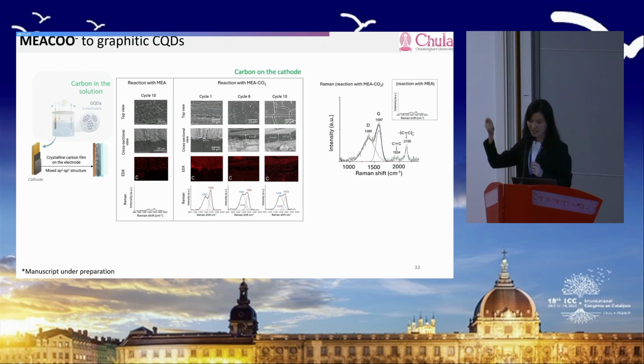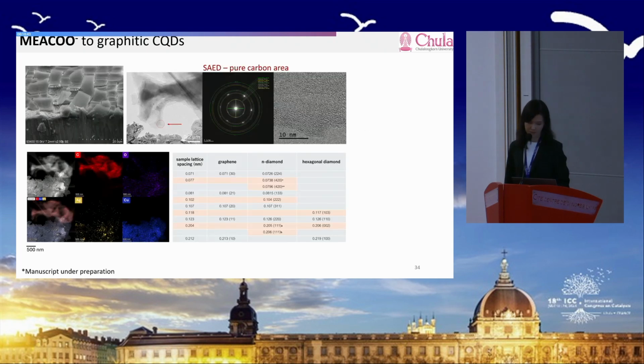And we take the electrodes and look at the electrodes. We see like a thick carbon film as well here, starting from cycle 1 to cycle 10. This is after cycle 10 without CO2, so there's almost no carbon deposit in that case. On this CO2 system, we have a thick carbon film, and it shows the graphitic nature from the Raman, and also we see some linear C2 carbon species as well, which seems to be our intermediates into this graphitic carbon quantum dots formation.